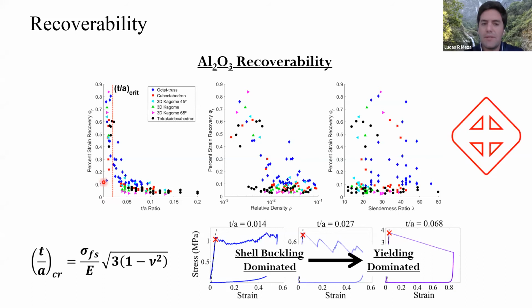But we were still seeing structures with a fairly low T over A that didn't really recover. There's a very wide spread, even past this ratio, where some structures were and some weren't able to recover. So this was kind of a weird open problem, and this is one of the big things that I'll get back to.